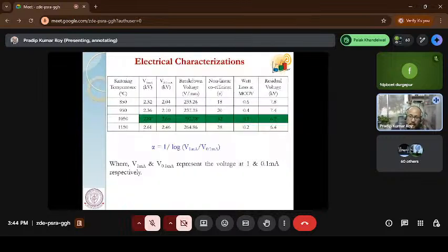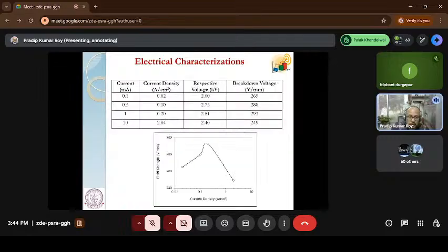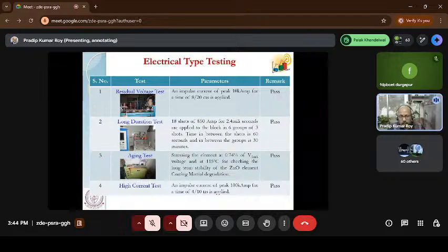I said earlier the breakdown voltage was around 120 to 140 volt per mm. Now we achieved around 300 volt per mm. So almost double we have achieved, just by reducing the grain size from 12 micron to 6 micron. Then we did some testing, normally the impulse testing called residual voltage testing, and high current testing. Residual voltage testing tells how much initial strength the body can withstand, with an 8 by 20 microsecond impulse. We are applying around 10 kiloampere current.